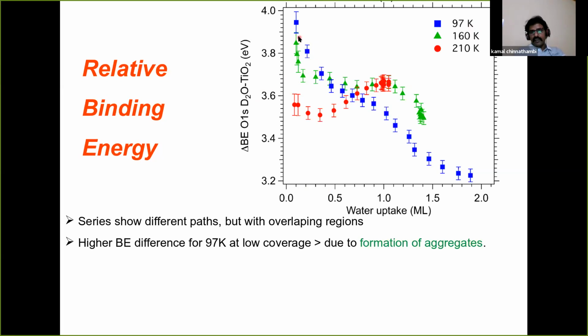So it's obvious that when the molecules are isolated, when you pour them, they are separated. But once you pour more and more, once more aggregates form, it is very well reported that whenever a network forms between the water molecules, the binding energy starts to decrease. That is what is happening with the 97 Kelvin. It keeps reducing even before reaching one monolayer. You can see that it continuously keeps reducing.